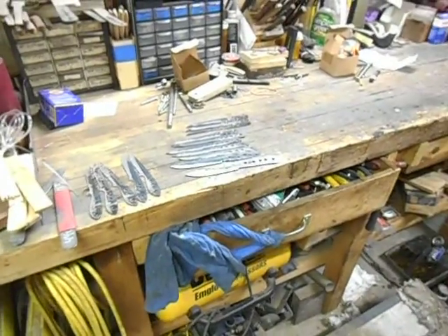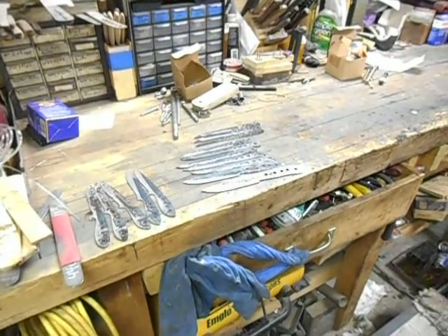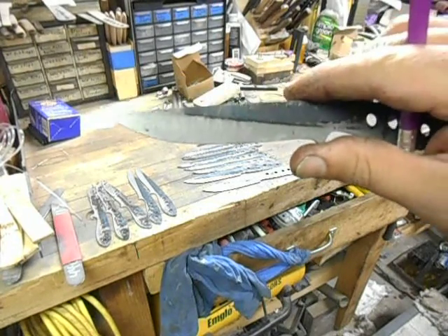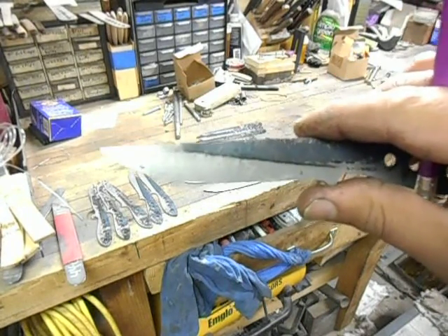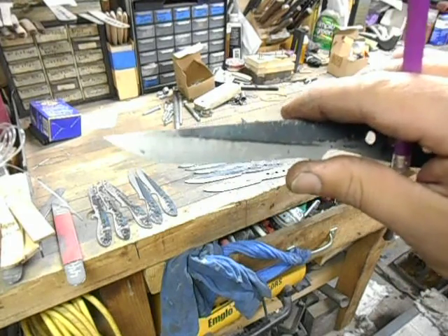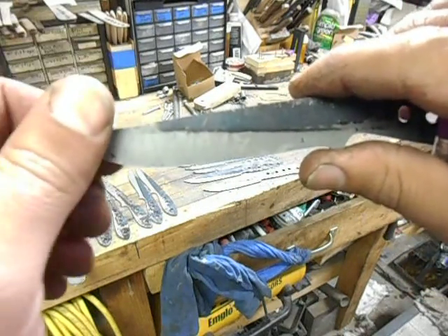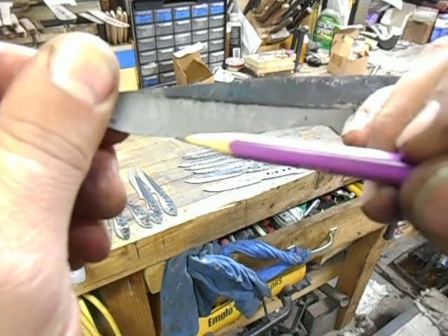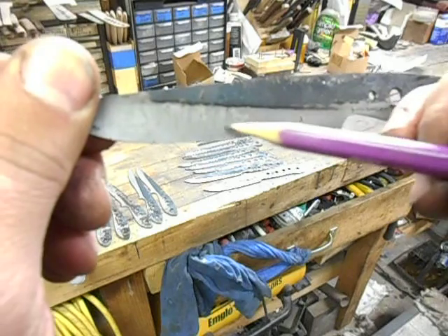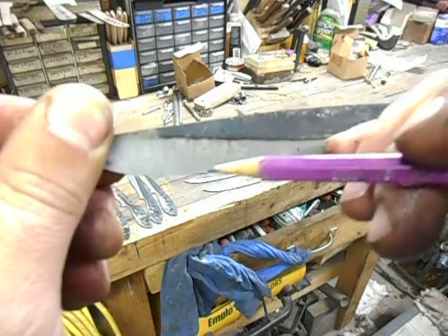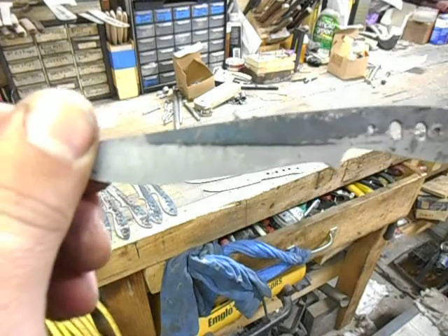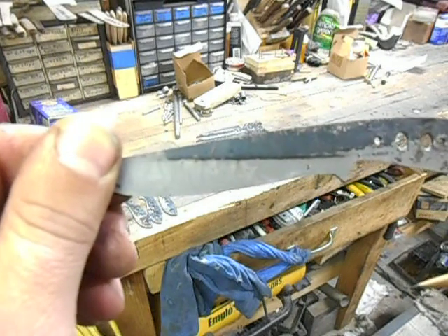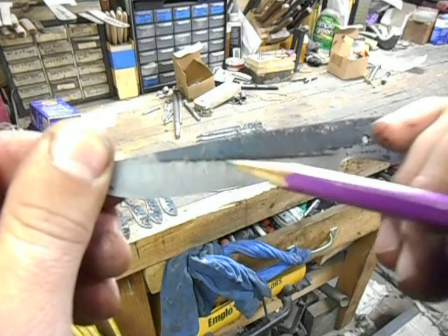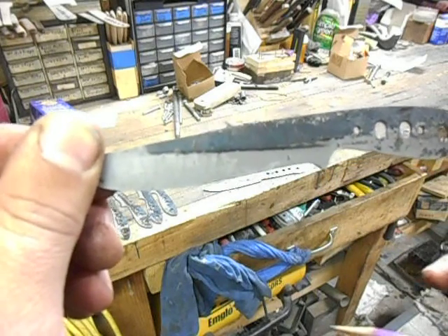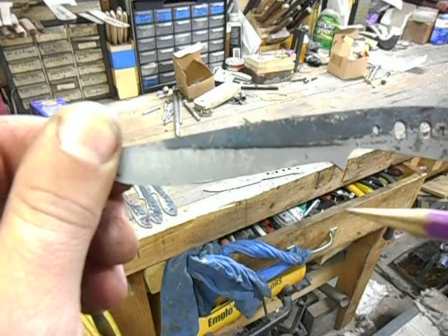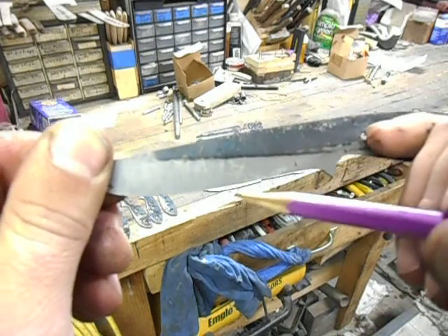So that blade is going to go through one heck of a shock being pulled from that nice toasty 1500 degrees Fahrenheit oven to a 50 degree room and then into 140 degree canola. And what will happen, and your biggest indication that this is happening, is the pieces of scale attaching to the edge. When you get that, what happened was that you either weren't hot enough in your kiln, or you couldn't get the blade out of the kiln and into the oil fast enough to get it hard, or you ground it too thin prior to heat treat.